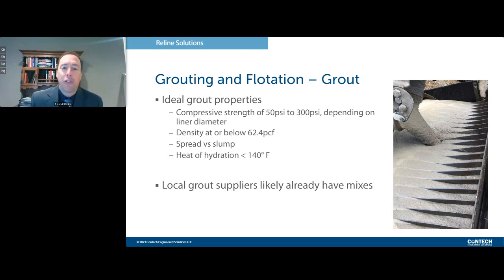The other item is the grout itself. Ideal grout properties that we're looking for are compressive strengths of 50 psi to 300 psi, depending on liner diameter. We also don't need a large density. So we're looking for actually a lighter density, anything lower than water. Remember, we were talking about filling the pipe with water, or even if we have to use bracing, the lighter the density, the less buoyant forces you're going to see act on that liner pipe. So we're looking for something that is a spread versus a slump. And the other thing is, to do that, a lot of entities will use some admixtures, and a lot of times that can increase the heat of hydration. We need a heat of hydration that's less than 140 degrees Fahrenheit. So we do get asked a lot whether or not we have sample mixes, and we do.